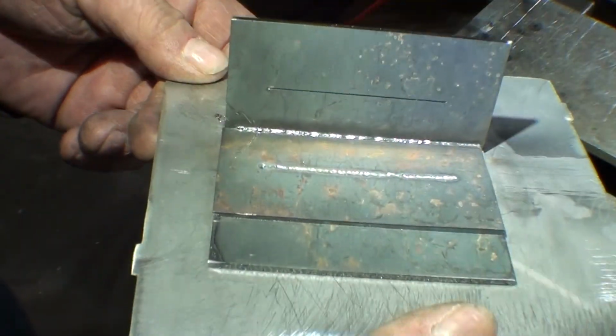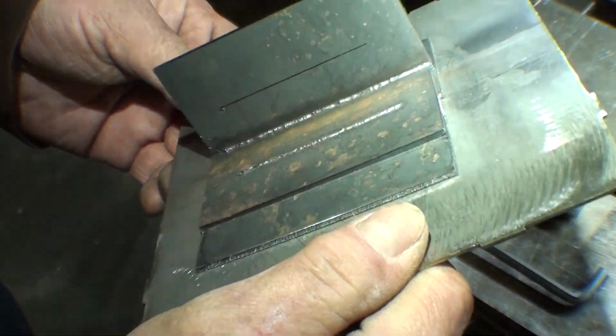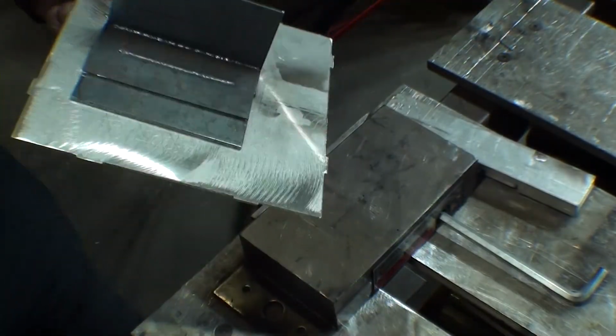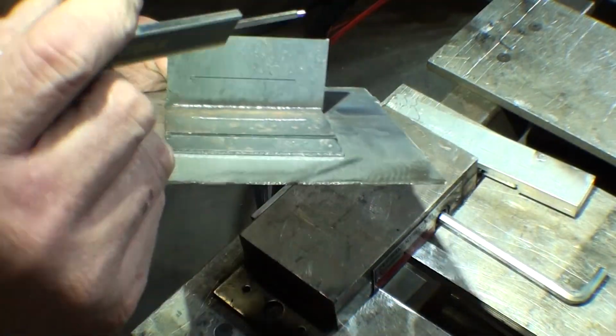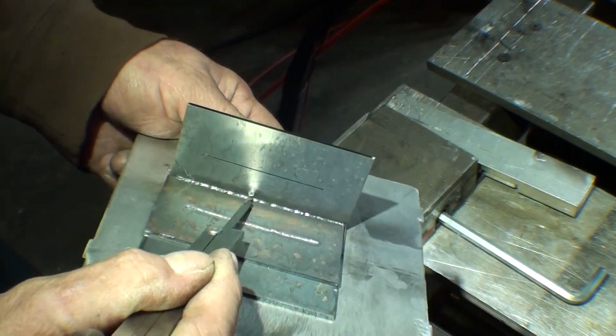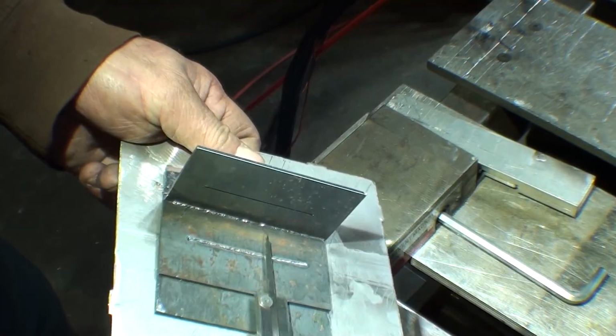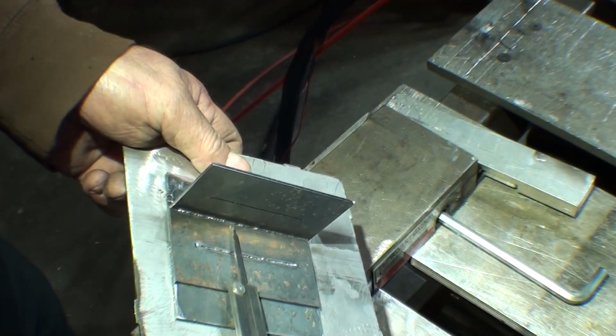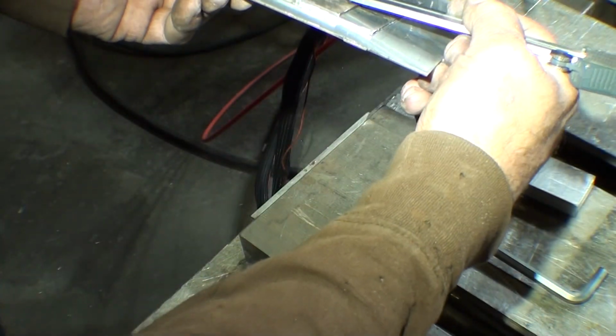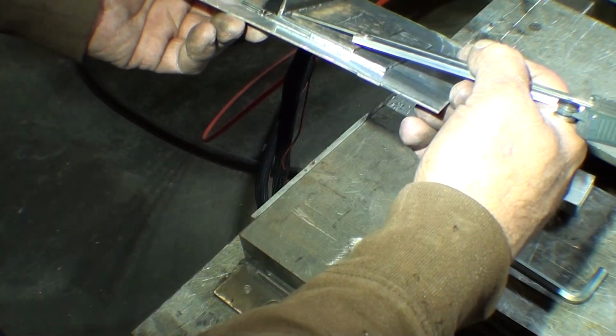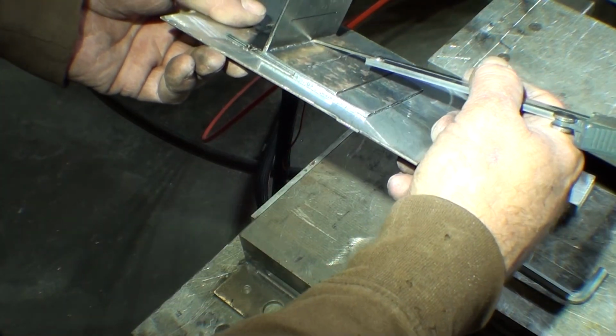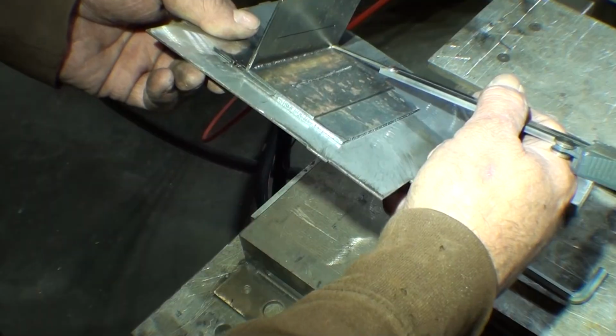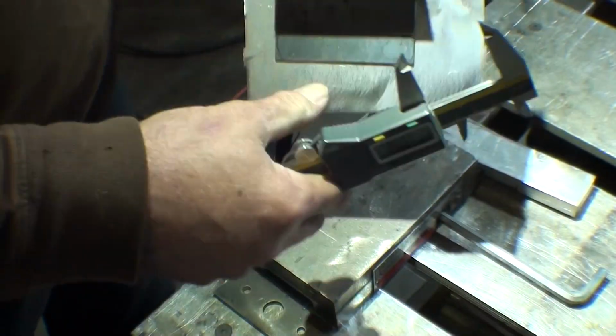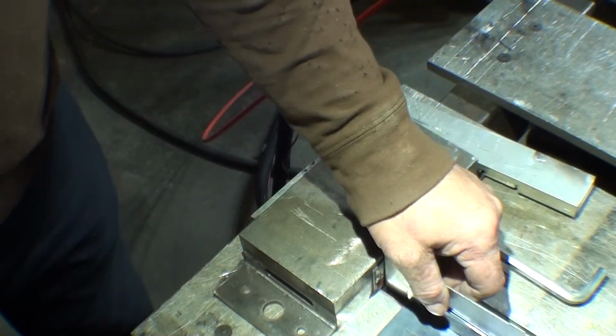In our case, we are still compliant, because the dishing effect I measured was only 0.03 millimeters, a tiny fraction of 1/16 of an inch. That is less than 2% of the 16th of an inch. Measured dish is less than 2% of the AWS tolerance. Nitpick that if you can. So I don't have a valley in the corner. How about if we do this side?